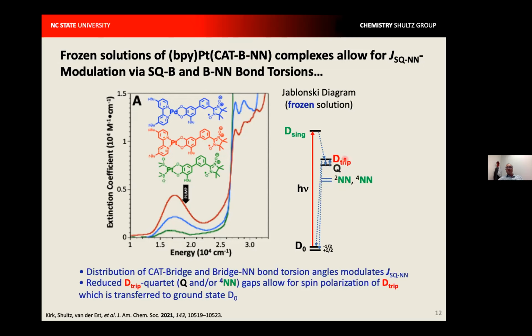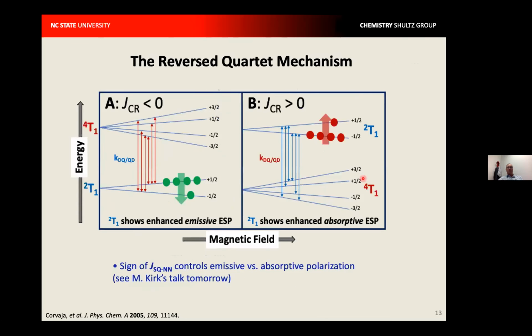What this means is it's conceivable under the right conditions that there's not only an equilibrium between D-trip and Q, but an equilibrium between D-trip and the quartet of the nitronyl nitroxide. And both of these equilibria can result in spin polarization by what's called the reversed quartet mechanism that's outlined in this paper at the bottom here. So in the reversed quartet mechanism, you get different signs of time-resolved EPR signals depending on the sign of the chromophore radical exchange. So here, the chromophore radical exchange is the excited state semiquinone nitronyl nitroxide exchange.